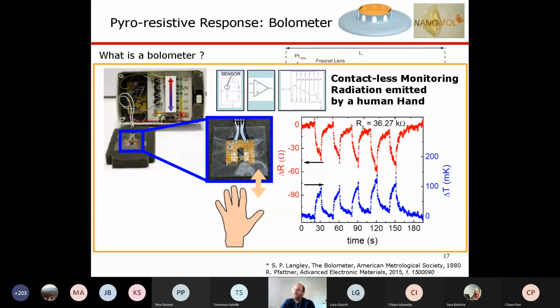And we took one of these pieces out again. We mounted it on a small holder and then connected some electronics to it. And then we're measuring the electrical resistance when I approach with my hand. So whenever the hand goes closer, the resistance goes down. Then it comes up, back again. Then the hand approaches, it goes down. So the resistance gets smaller when the hand is heating this tiny little film. We can back calculate after calibration the temperature, and we could see that locally this film was heated only for 100 millikelvin. That's a very small number. So they are very, very sensitive temperature sensors, in fact.